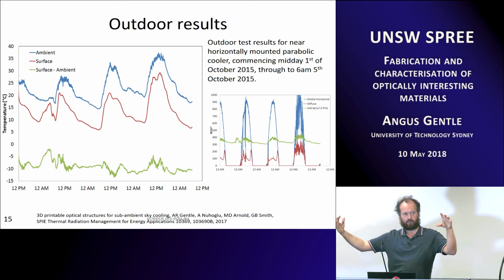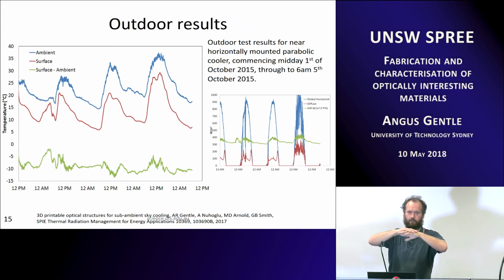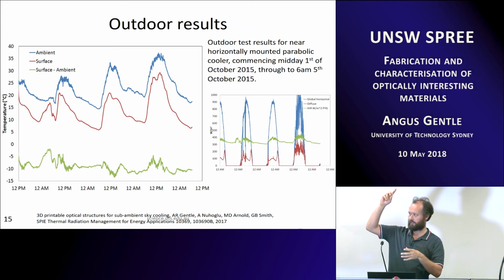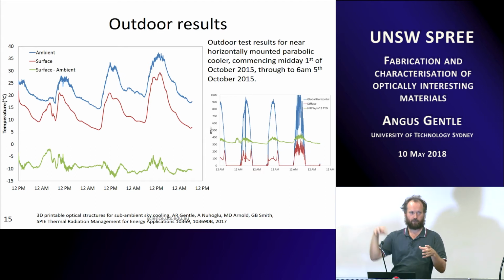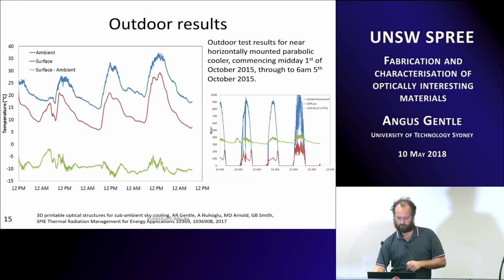So if you had full clouds everywhere, it's not going to work, because you'll still be concentrating towards a big cloud which is warm. But if you've got patchy clouds where you get extra sunlight coming in because it's bouncing off the cloud, you can still get, with 200 to 300 watts, 10 degrees, or in that case up to 5 degrees below ambient temperature continuously, which is quite a fun little game to play. So it's just looking at spectrally all different angles of not just your surfaces but the environment around you as well, and exploiting that as much as possible.